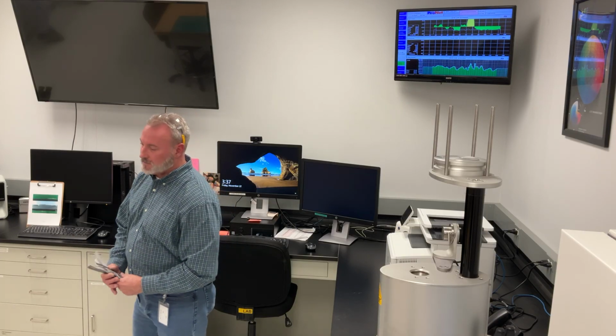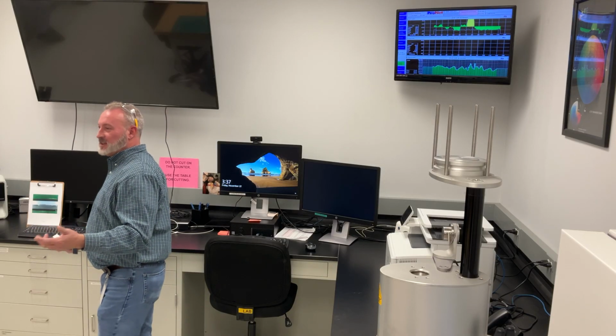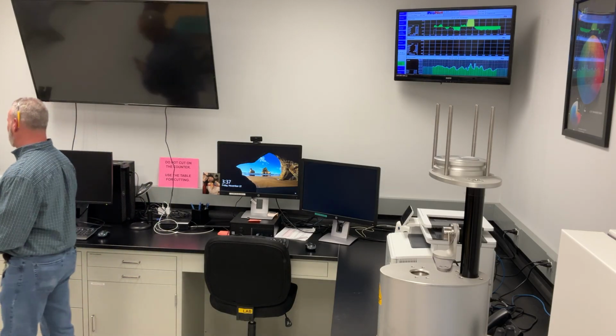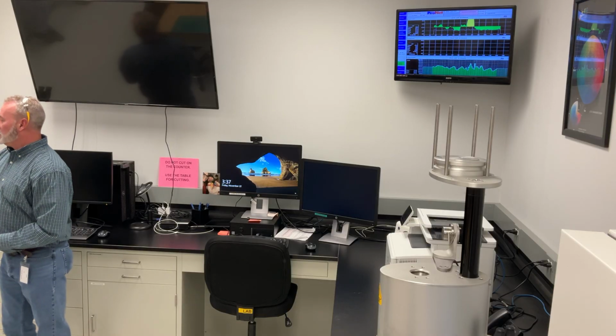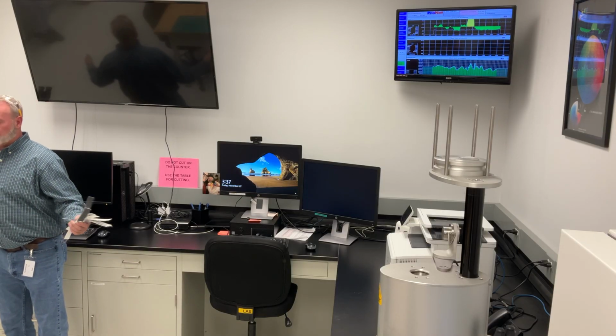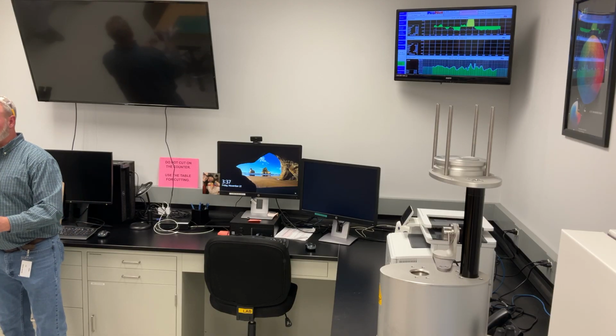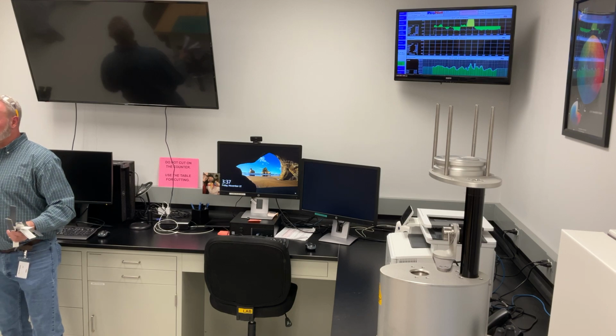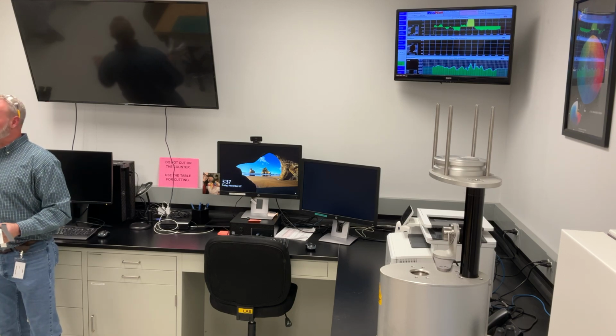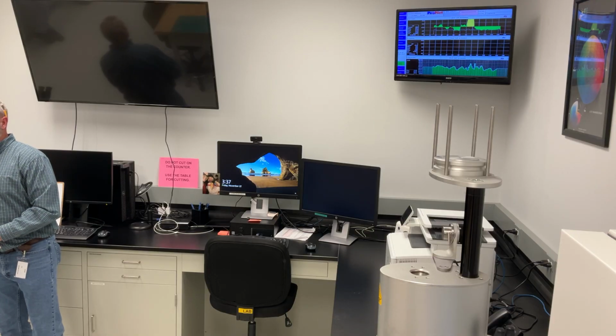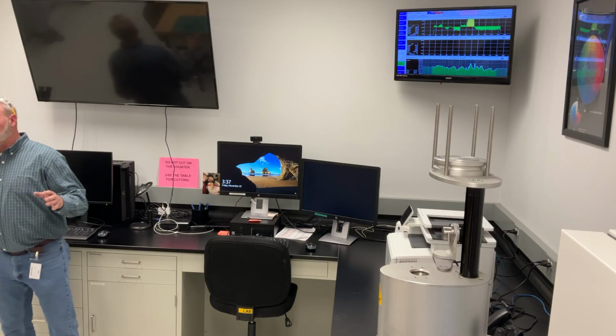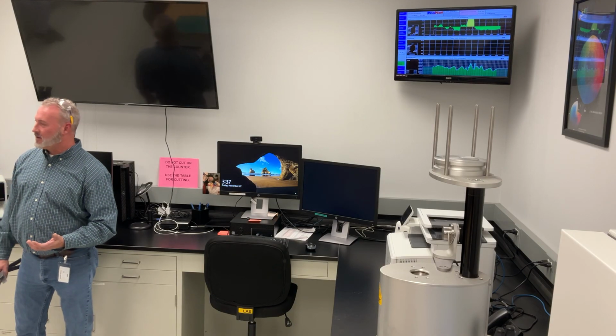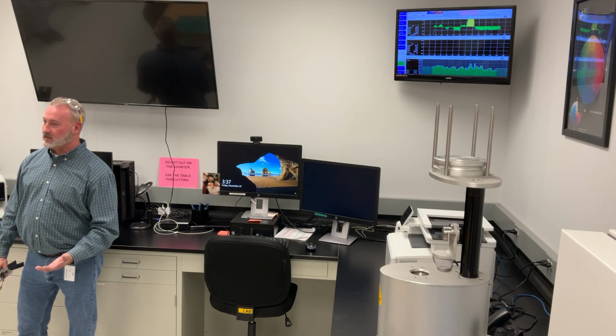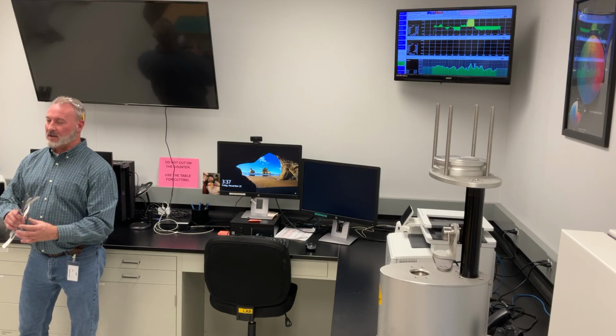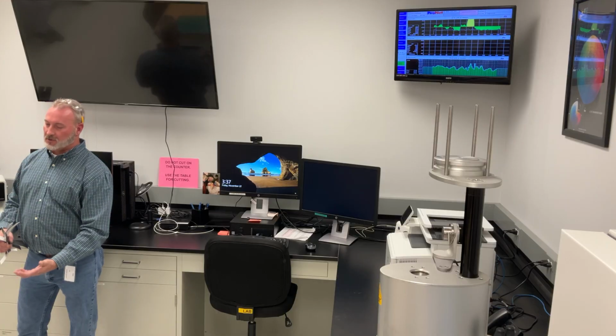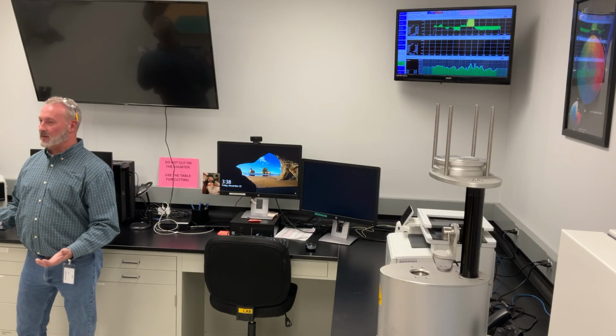And yeah, like Big Daddy was talking about your fleece adhesion, right? The guys last night asked the question of, hey, the overall average on the fleece adhesion was above 3. 3's the minimum spec on it, but there were certain sections of the sheet that were like a 2, and they were upset because quality wouldn't let them keep those sheets. Well, the reason we wouldn't let them keep them is fleece has been marketed as an impact resistant type product. But what it's really good for is gluing that product down. And if there was a low spot or you didn't have good fleece adhesion in a certain area of the sheet and it was glued down, it was more susceptible to pull up over time.